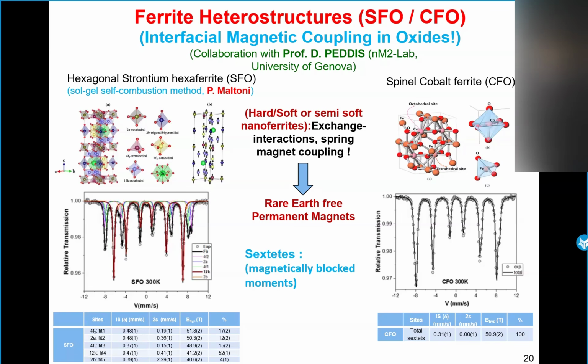We also performed the measurement at 77 Kelvin, but at 77 Kelvin, we observe a net increase of the value of the hyperfine field of the 12k site, and we observe more overlapping. So the discussion is better at room temperature. For the pure cobalt ferrite, we observe just the presence of sextets, asymmetrical and overlapping. From that, we just obtain the mean information, indicating the presence of octahedral and tetrahedral sites, corresponding to a blocked magnetic moment.